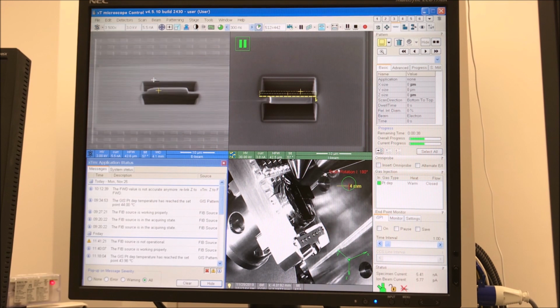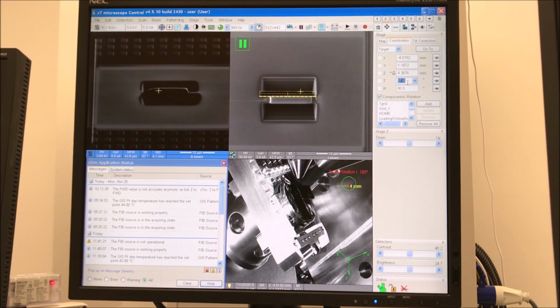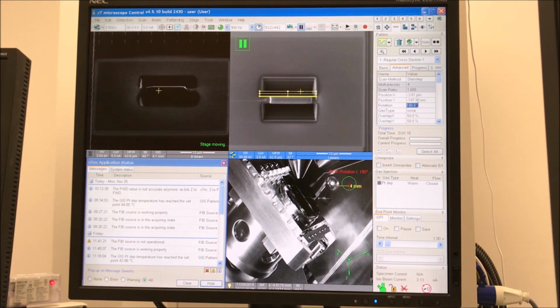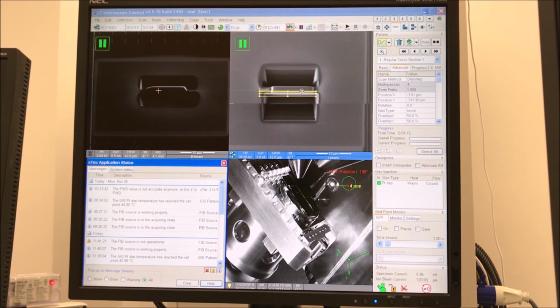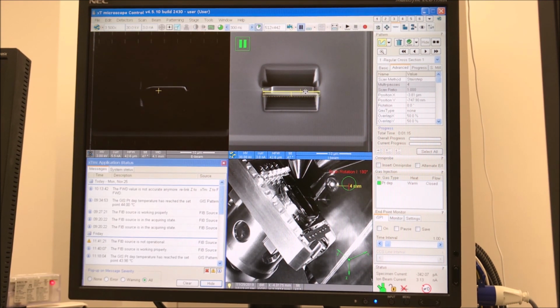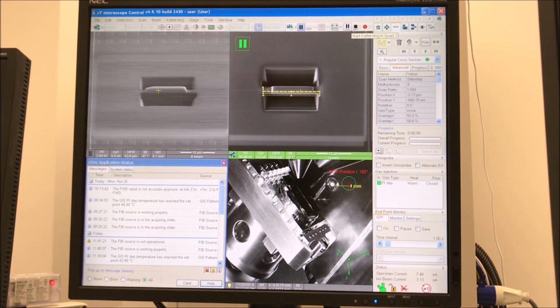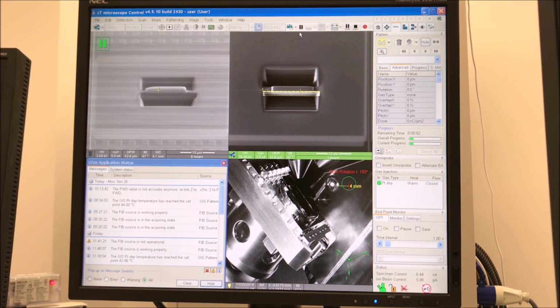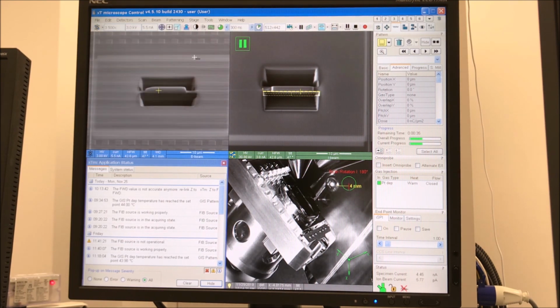You can see here I'm also using live electron beam imaging while milling, and I'm also using averaging. That's especially helpful when your ion beam current is high relative to your E-beam current. Now I'm tilting to 47 degrees, so 5 degrees the other way off from normal, rotating the pattern back to 0 degrees, and then executing basically the same pattern. I made a slight change to the dimension, the Y dimension, I should say.